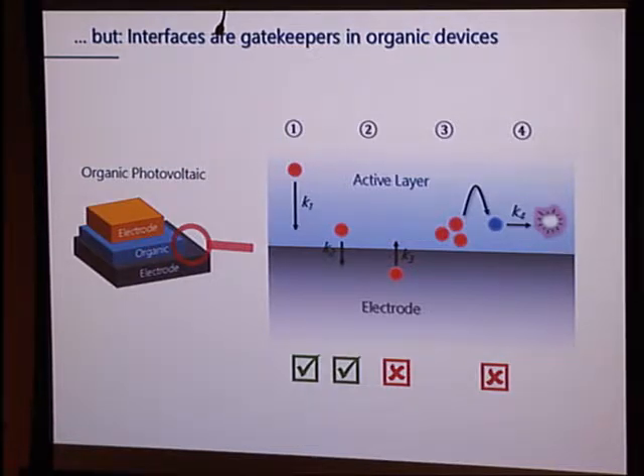So if I take the example of an organic photovoltaic again, then somewhere deep in the material up here, I have a generation of carriers by some mechanism, and they get eventually swept towards the electrodes by chemical potential gradients and applied electric fields. And when they do so, they diffuse towards the electrode, and we hope that we can harvest them. So there's a rate constant or a flux with which these carriers make it from the active layer into the electrode. There is, of course, the reverse process as well. And that one you don't want. You don't want carriers to jump back into the active layer because that is a loss process.